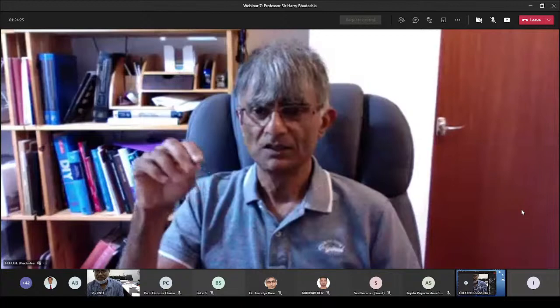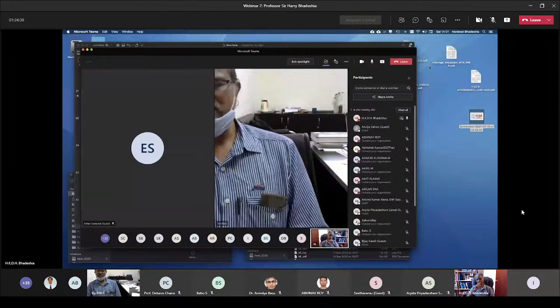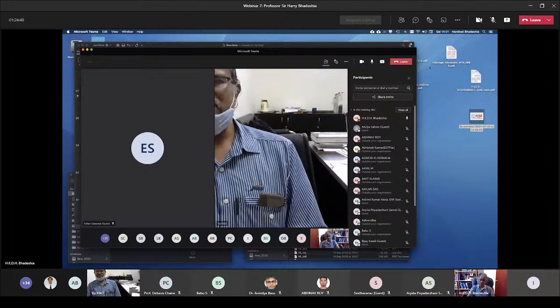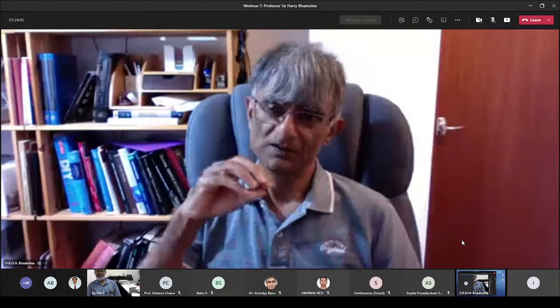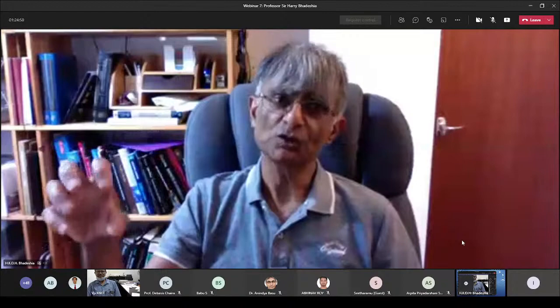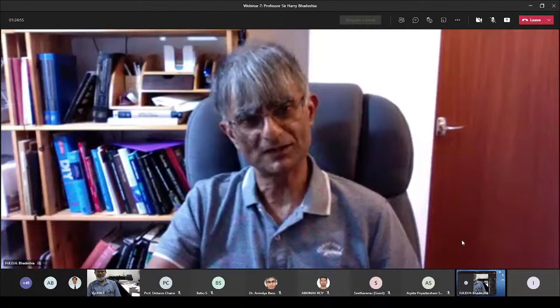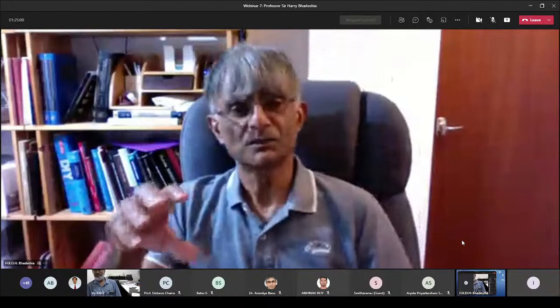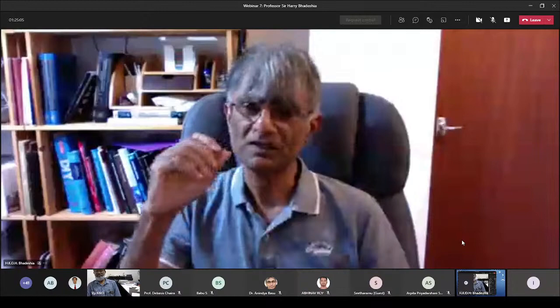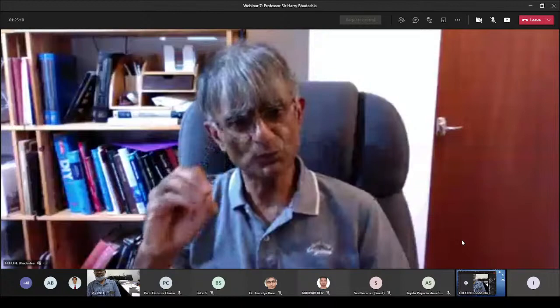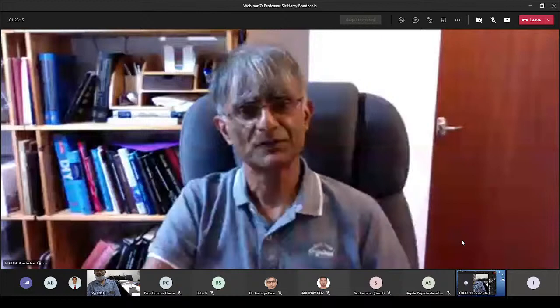Yeah. So it is straightforward to do a calculation to see whether the concentration of carbon in the austenite is sufficient for it to be retained or for it to form martensite. So in general, when you have commercial TRIP-assisted steels, they ensure that there is sufficient carbon enrichment to stop the martensite from forming. Now, there's one more thing. You mentioned the blocks of austenite. The blocks I was talking about are very large, something like 50 micrometers in size. But you will always get some blocks. But if they are small in size, then they don't trip. Okay, thank you.